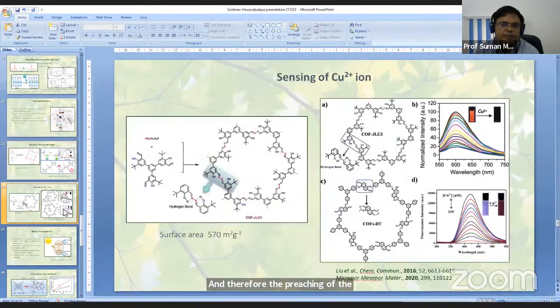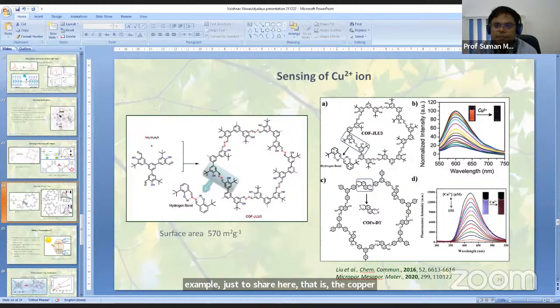Now, another example I would like to share here is the sensing of the copper ion. Here again, you see there is some covalent organic framework formed, and this gives a beautiful red-orange color. But when you treat this covalent organic framework with copper ion, this copper ion gets attached to some place inside this covalent organic framework through coordination interactions. And the red-orange color or the fluorescence color disappears. And in this way, it is possible to detect the copper ion in a solution. The surface area of this covalent organic framework is not great, but the importance is that among the various ions, it can detect copper ion through switching of the fluorescence inside the cavity.